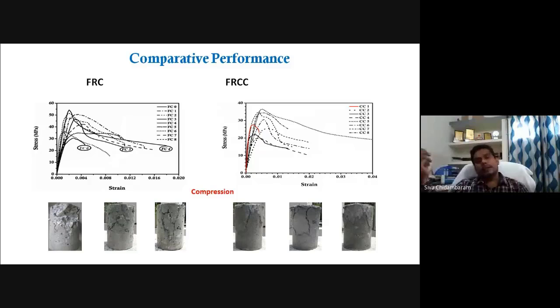In a study conducted by myself, we used fiber reinforced concrete and fiber reinforced cementitious composite. If you closely look at the stress strain diagram, you can understand that the stress of your fiber reinforced concrete is higher than the stress of the fiber reinforced cementitious composite. The strain is 2 times higher than the conventional fiber reinforced concrete. So what happens when it comes to damage capacity? If you look at the bottommost cylindrical sample, you can identify the different types of failure pattern. Conventional concrete is split apart, fiber reinforced concrete holds the cracked portion together. The composite is also holding, but the crack intensity is not much. That is the beauty of fiber reinforced cementitious composite.